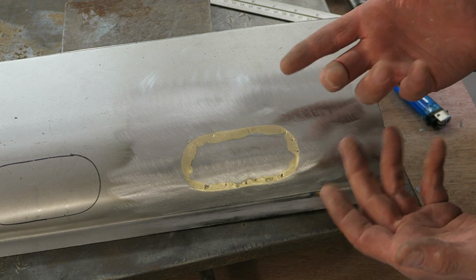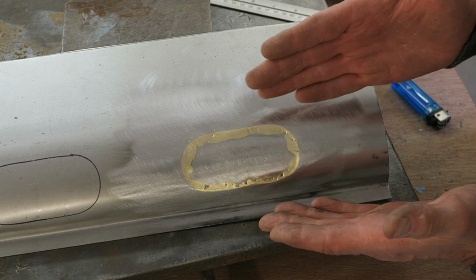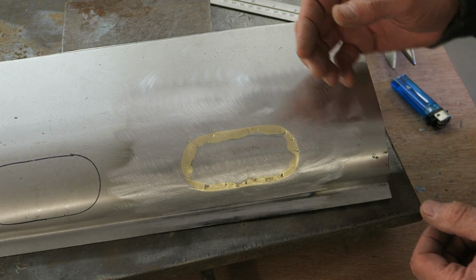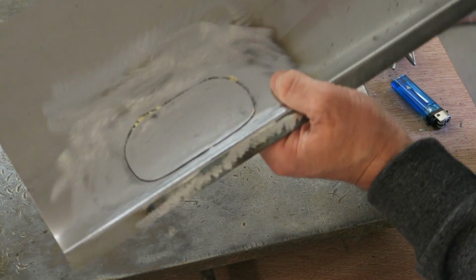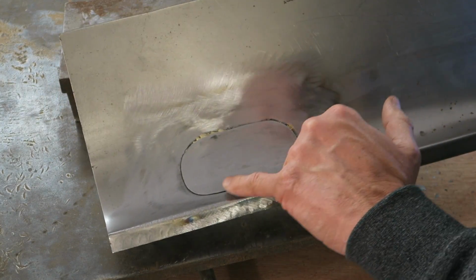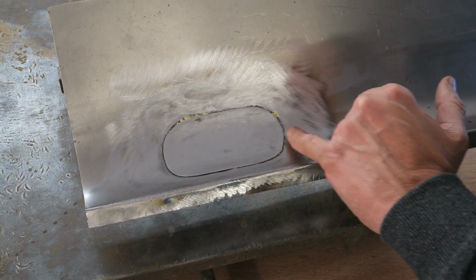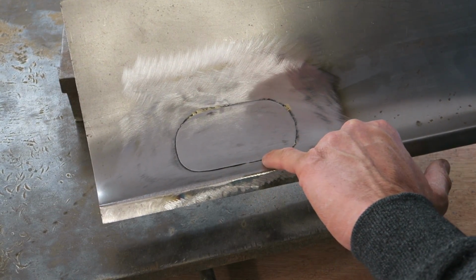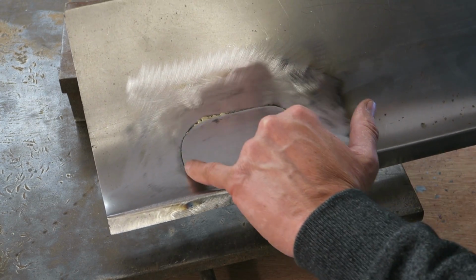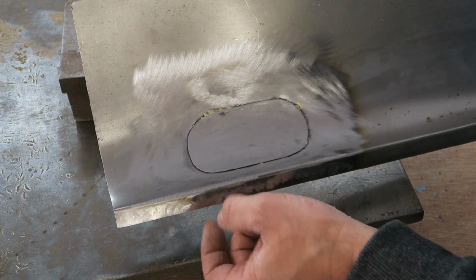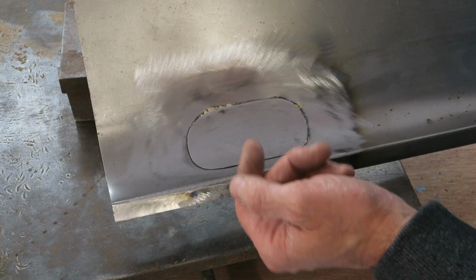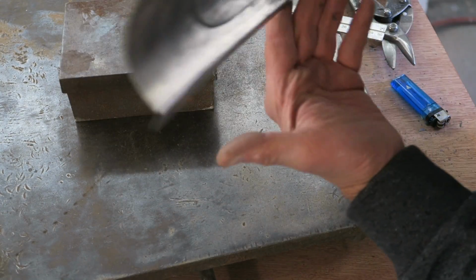If it was to rust from behind, it would have to rust all the way through until you saw any evidence on the outside. However, we do have a bit of a gap here. If you couldn't get from behind to seal this up, this gap would become a massive rust trap very quickly, and you'd have corrosion set up between the two panels extremely quickly.